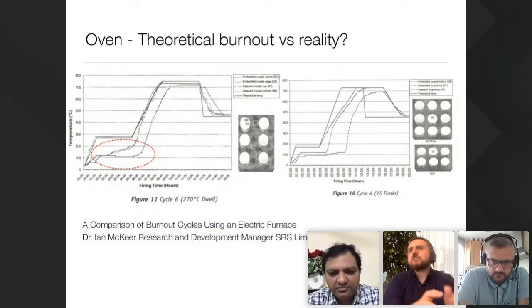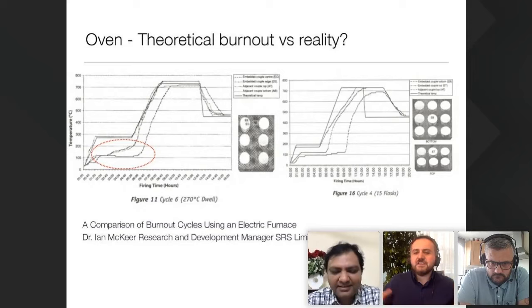Let's imagine the case where you didn't wait outside - you just mixed, poured it, waited let's say 10, 20 minutes, and then put it inside. That thing has a lot of water, a lot of humidity inside. So what happens? You put it at 300 degrees for the first step, let's say, or 250 degrees.